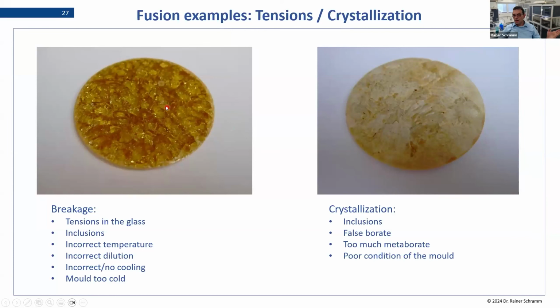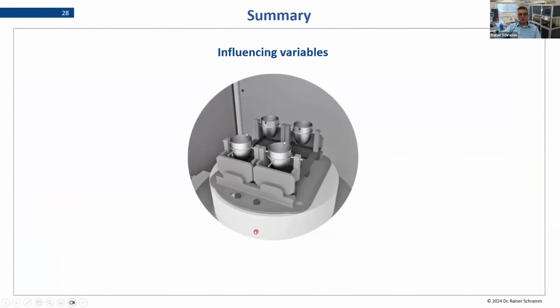And tension means, like I mentioned, that it sticks to your mold, and then while cooling down, it's cracking. And then it could be that you should look for inclusions. So you have still particles which are undissolved. And this, of course, you can solve by grinding better your sample, by diluting, or by heating higher. Yeah, so these are all possibilities to increase the conditions, to get better conditions.